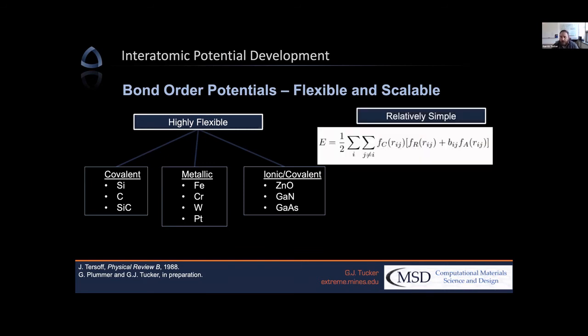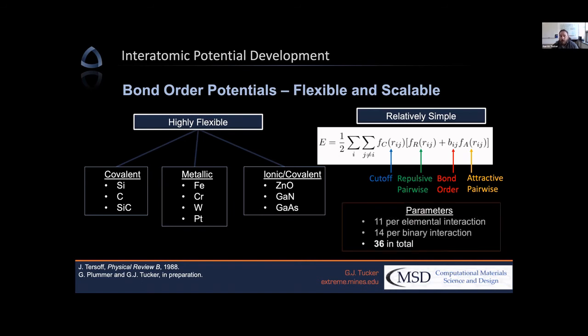One of the things we liked about this was that the energy functional for describing the potential between the atoms is relatively simple, in the sense that there are basically four different aspects of the functional. There's a cutoff function, a repulsive pairwise term, an attractive pairwise term, and then this bond order term, which gives us a lot of the tunability in the energy functional. If we think about the titanium carbon-based MXenes, which we'll be talking about today, we have 11 parameters per elemental interaction and 14 for each binary interaction. So for this particular system, it gives us 36 parameters in total to optimize.